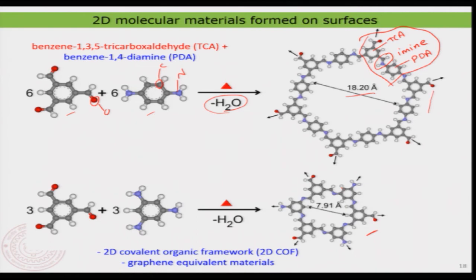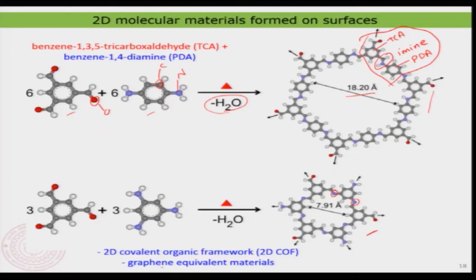This is nothing but graphene or doped graphene — a graphene-like structure with doped atoms inside. If you ask a graphene chemist, this is what they do daily: dope nitrogen or oxygen atoms within the graphene layer for band gap engineering. Graphene has zero band gap, which is not useful for electronic devices. You need to open up the band gap. Here, by doing chemistry on surface, I have made a graphene-equivalent purely two-dimensional material — and the two-dimensional nature comes from doing the experiment on the surface.